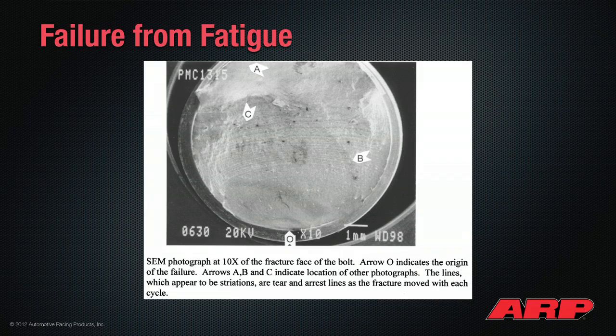This is what happens when you get it wrong. So we've got a failure here. This is a fatigue failure as a result of either picking the wrong material or from not having the fastener preloaded correctly, to where the dynamic load and the bending load exceeds the fatigue life of the material. So you can see the origin, you'll start a fatigue crack here. If you think about the paperclip analogy, if you bend that thing backwards and forwards, it's going to fracture and break. So you start with a crack initiation, typically on the inboard side of the rod, because if you think about the bending load that's going on, the largest concentration is going to be the inboard side of the bolt. And those cracks open up and ratchet.